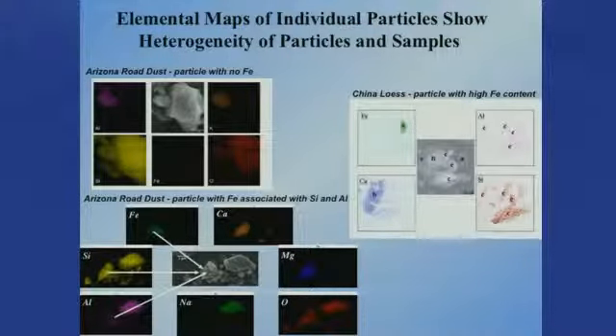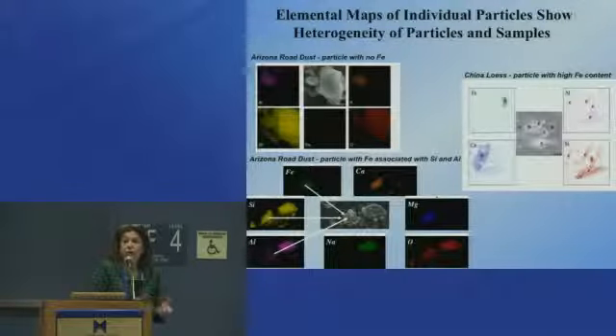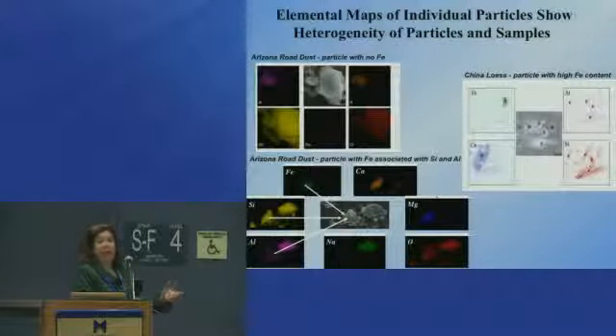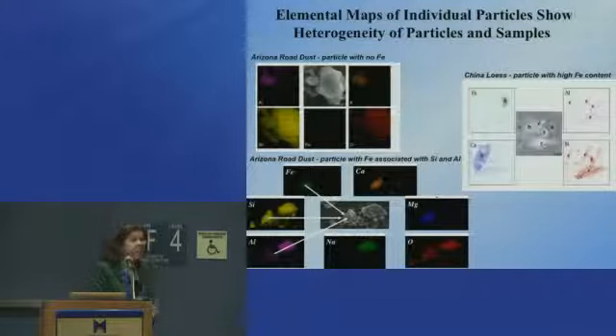The important point here is that elemental maps of these particles again show heterogeneity. You can have a dust particle that has no iron, so here we have nothing there. Here we have a dust particle shown in the middle, which has iron, but it's also co-located with silicon and aluminum. So this is iron in an aluminum silicate clay. Here we have a China loess particle, which has high iron. Maybe that is in fact hematite, iron oxide, but clearly it's more than just one type of iron in the particles, and they're distributed within the particles.